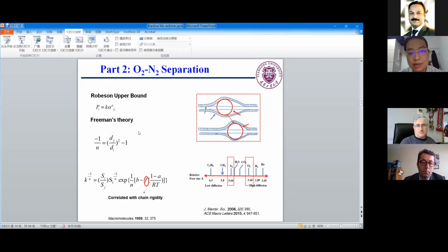Robeson summarized thousands of membranes, and he got the empirical trade-off curves called the Robeson upper bound, in which permeability and selectivity have a trade-off: the higher the permeability, the lower the selectivity, because the power n is negative. Based on this, Freeman also theoretically analyzed it. So what's the effect of n? The power n is related to the kinetic diameter difference of these two molecules, and the parameter k is related to the chain rigidity, the pores, and the free volume of the polymers. We cannot change the diffusion coefficient, and we cannot change n because the gas molecule size is fixed. We can only adjust the free volume and the rigidity of the polymers.